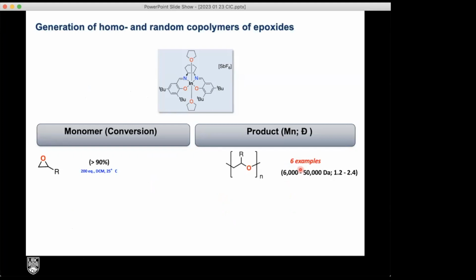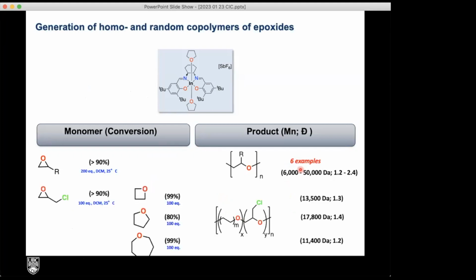And then he was able to show that for a number of different epoxides, this catalyst was excellent for forming polyethers. He was able to show that he can homopolymerize a number of different cyclic ethers and copolymerize epoxides with these ethers to generate a mixture of different polyethers with a variety of different structures.